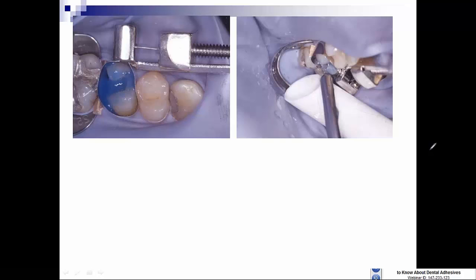So in this image, just as a very easy, solid, clinical, reproducible way, the picture of moist dentin, if you could think about this, is the absence of picking up your air syringe to dry the tooth. And the way we can create this reproducibly is place phosphoric acid. This is a total etch technique, etch and rinse technique. And then we rinse the acid off. And after we see the blue, or whatever the dye of the acid is, we need to leave the water on for at least one or two more seconds to be sure that we've gotten all the residual acid and all the residual material off from the phosphoric acid gel.